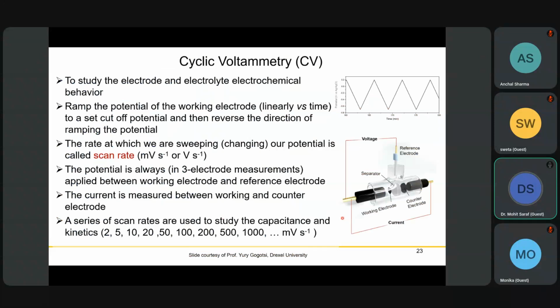The very first technique, and personally I like this one very much, is cyclic voltammetry. Basically it's used to study the electrode and electrolyte behavior, how the interface works. In this technique, we ramp the potential of our working electrode with time, linearly, to a set cutoff potential. So we set the potentials and linearly sweep the working electrode, and when it reaches that point, we reverse the sweep and it brings it back to the original position.